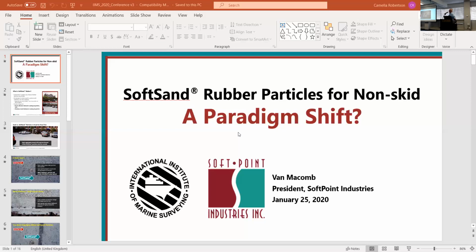All right, so generation 2, I would say in pleasure boating, most of the paint companies, at least in the US, virtually all of them have gone to either a polyethylene or polypropylene bead. And some of them will tell you it's a low molecular weight polyethylene, which essentially is a wax. So from a comfort standpoint, it's a step in the right direction because you're getting away from the tough blast aggregates. But we really feel that the best solution with an elastomeric coating is going to be an elastomeric particle, which is what Soft Sand was developed for.